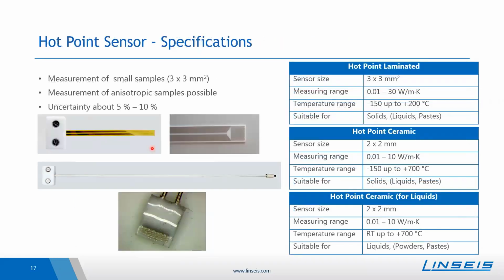The hot point sensor, as mentioned, is for small samples and also very useful for anisotropic samples, because it only has here the small tip as a sensor, and because of that, one just needs a 3 × 3 mm squared sample to be able to perform some measurements. Also, the sensor is useful for solids, liquids, pastes, and powders. And with the ceramic versions, one can go up to 700 degrees Celsius.